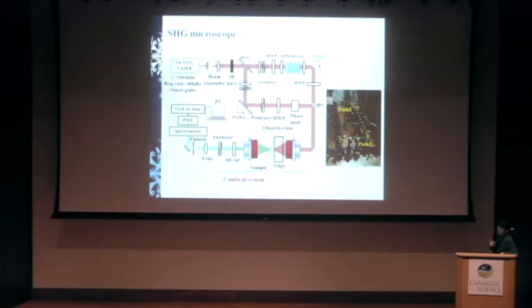This is the optical system that we are using for our experiment. We use an Nd:YVO4 laser as a fundamental wave, and we separate our optical system into two paths: one path is for the fundamental wave, and the other is for the reference wave. For the reference wave, we normally use a difference wave for the interference experiment to observe the 180-degree domain boundary, but this time I'm not going to use the interference experiment, so I only use path one for our experiment today.